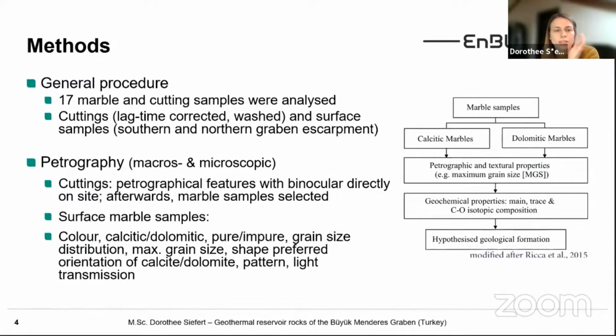So about the general procedure and the methods. In total, we have 17 marble surface and cutting samples, which were analyzed by different petrographical and geochemical methods. The cuttings are taken as usual in 5-meter intervals and were lag time corrected, washed and dried, and investigated on-site by binocular regarding the petrographical features, and then we selected samples within the marble horizons, which were then investigated further also with polarized microscopy.